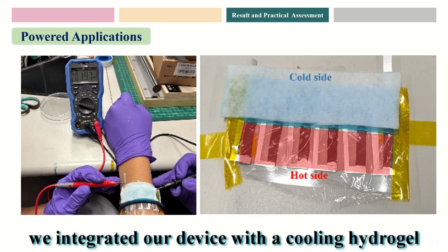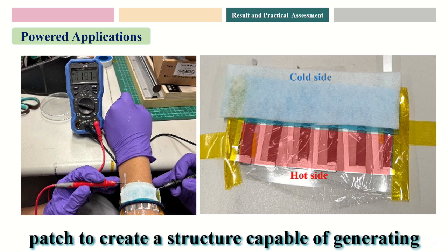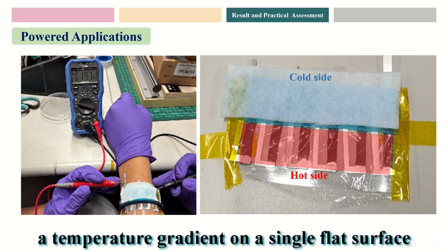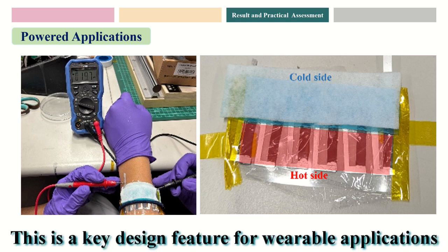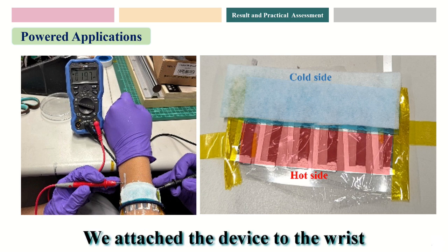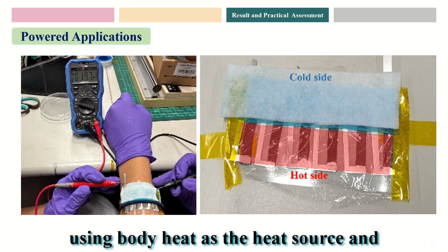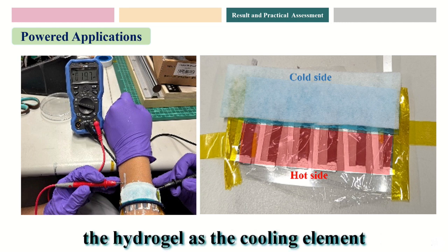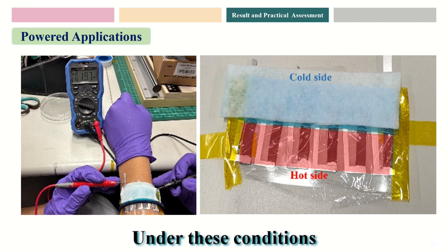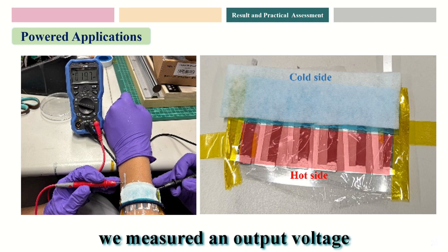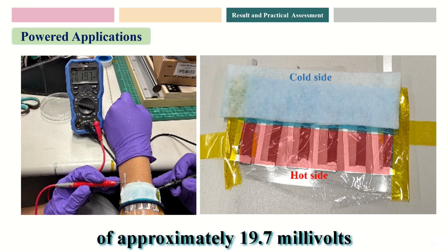Finally, we integrated our device with a cooling hydrogel patch to create a structure capable of generating a temperature gradient on a single flat surface. This is a key design feature for wearable applications. We attached the device to the wrist, using body heat as the heat source and the hydrogel as the cooling element. Under these conditions, we measured an output voltage of approximately 19.7 mV.